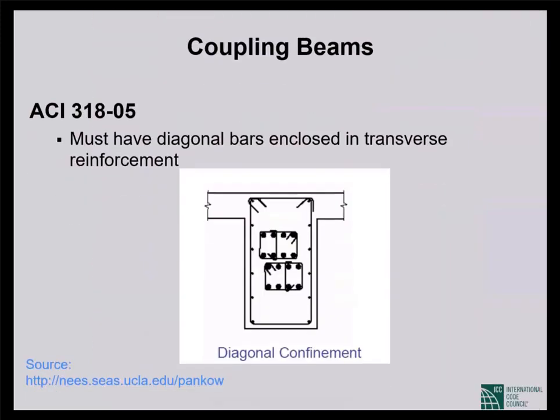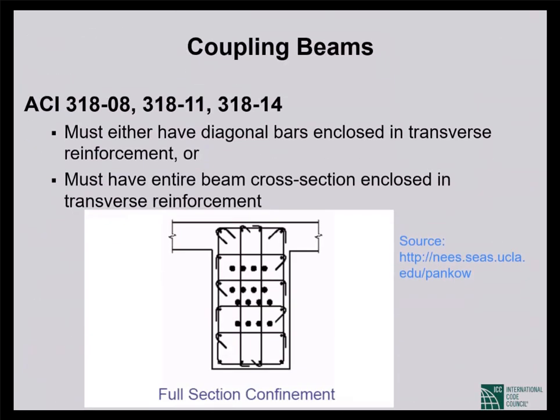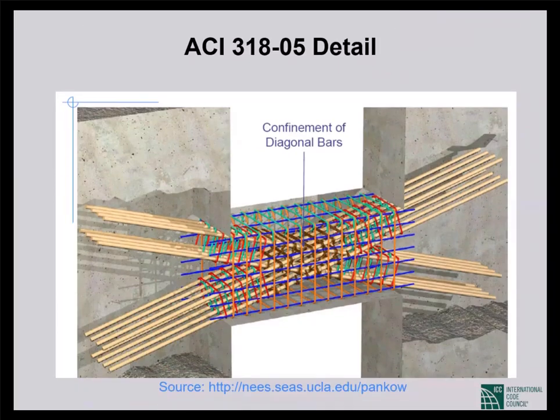So up until ACI 318-05, the only choice our code provided was the confinement of the individual diagonals. But then, based on quite a bit of testing, John Wallace showed that we could provide an alternative where we confine the entire coupling beam section and not try to confine the individual diagonals. So this is shown in the picture. You see the confinement reinforcement, and I will show you better pictures from John. So this is individually confined diagonal reinforcement. This is the only solution that we had under ACI 318-05.